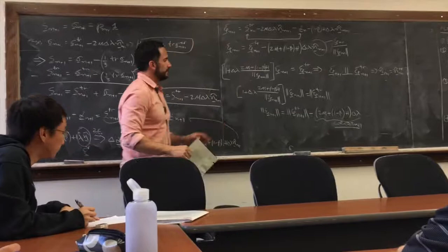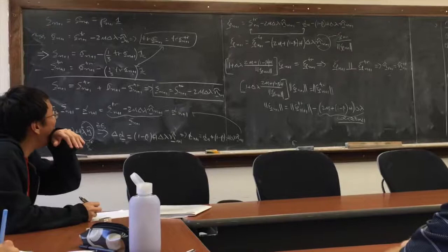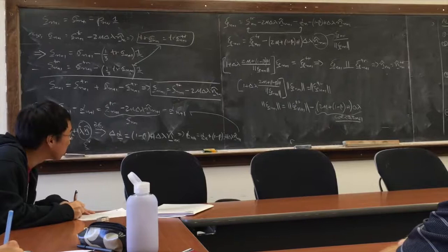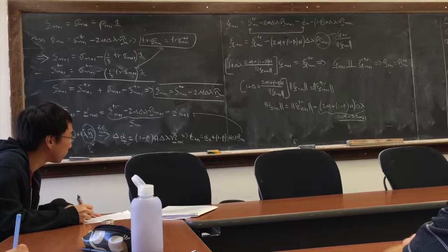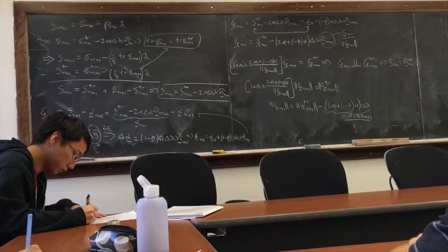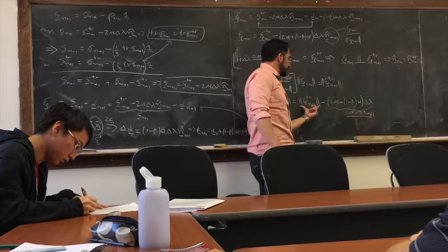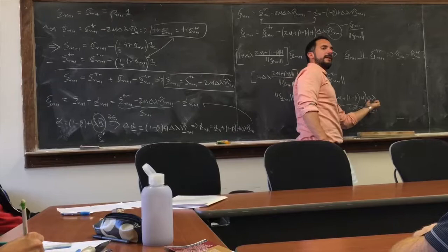I compose a trial back stress. That trial back stress happens to always be in the right direction. That's what we just found out. Its direction is correct. The strength of it, the magnitude, is incorrect. So when it overshoots by a certain amount in the magnitude, it gets corrected by a certain amount that depends on the plasticity. But it also depends on what kind of model you're using.